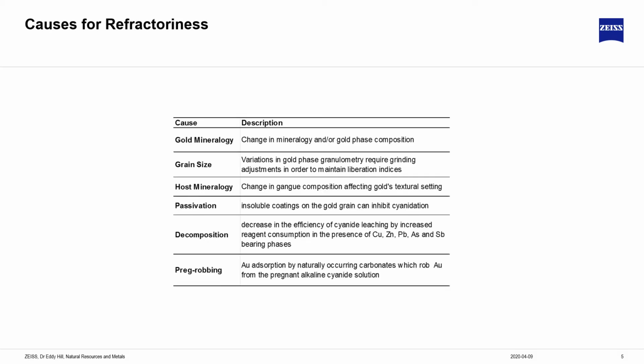Causes for refractoriness, or the affinity of the gold to remain in the ore material rather than be recovered, are multiple. It may be that any one of these causes is impeding the recovery, but the likelihood is that many of them interact to cause refractoriness. Changes in mineralogy of the gold phase composition may be a cause of refractoriness.